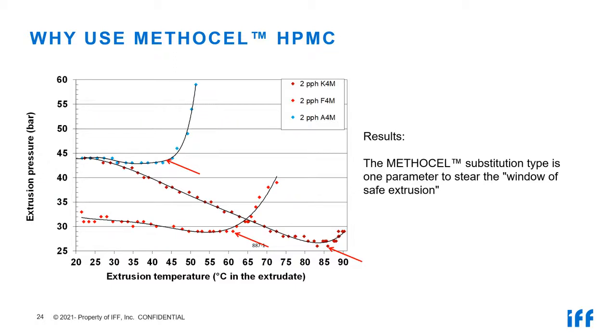METHOCEL F4M is a second example, the other red curve, which shows significantly lower extrusion pressure and also a lower gelation temperature, somewhere in the range of 60 degrees. And for special cases, we can recommend also the A chemistry, the pure methylcelluloses. However, they have a combination of all disadvantages you have seen so far. They show high extrusion pressure and a very small window of safe operation, because the gelation temperature in this case is already at 45 centigrades. However, there are reasons to use it, and it is used in the market. For instance, the METHOCEL A grades give a wonderful shape retention in complex profiles. This is a benefit we should mention. Next slide, please.